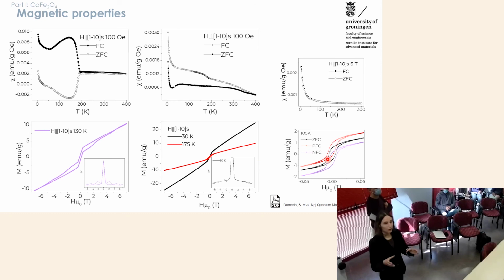Since here we don't have any specific strain from the crystalline substrate, because it's forming all these domains that allow the structure to relax, we also expect to see that both phases are present down to low temperature, because there is not this strain stabilization of the A phase.